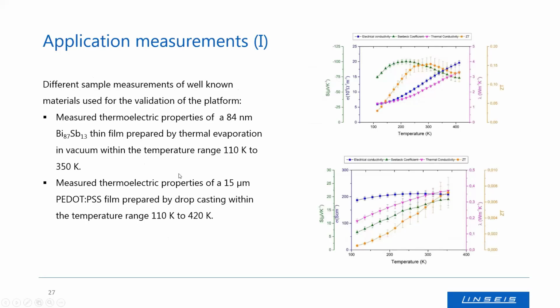So let's have a look at 3 applications. On the upper picture, you see the analysis done on a thermoelectric film made from bismuth antimonide. The film with a thickness of 84 nanometers was prepared by thermal evaporation. And what you can see is in pink, the thermal conductivity over temperature. Blue is the electric conductivity. Green is the Seebeck coefficient. And from these values, the figure of merit is calculated and shown here in yellow color.